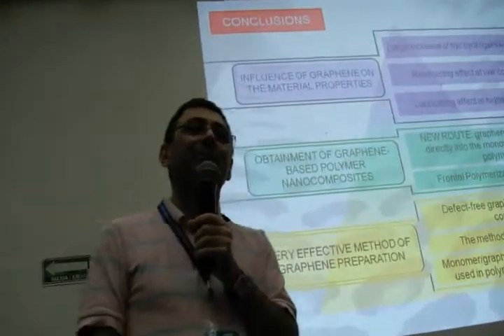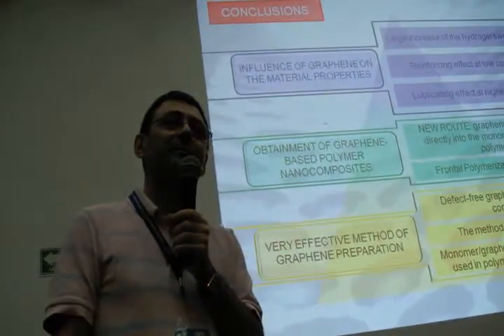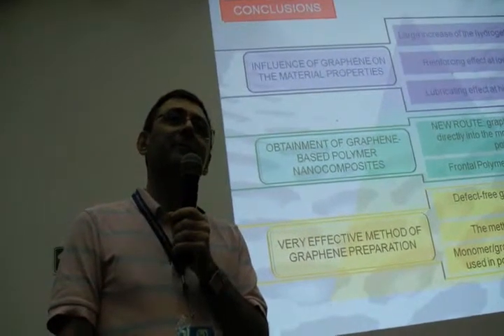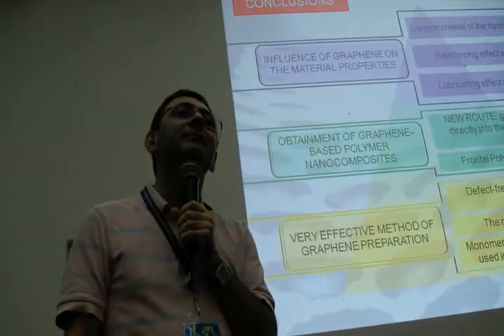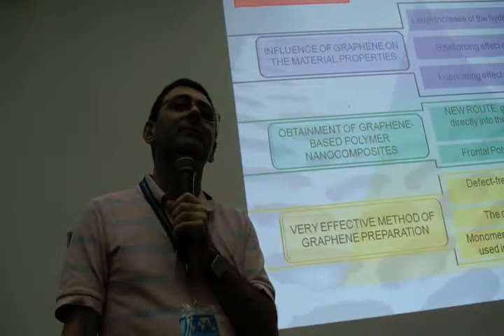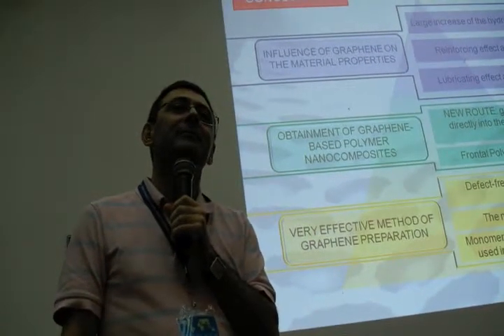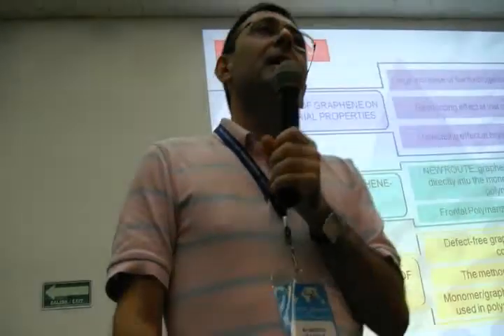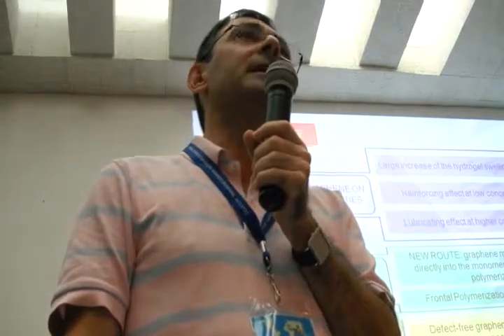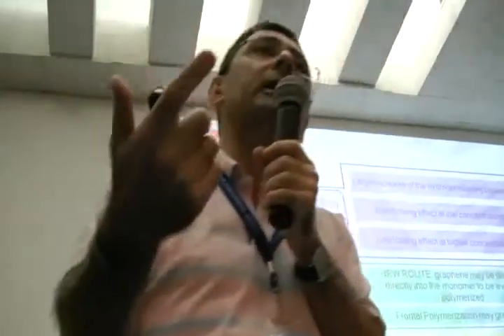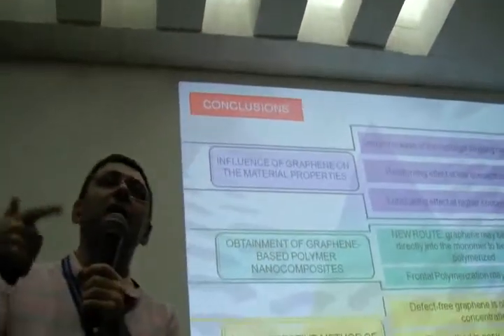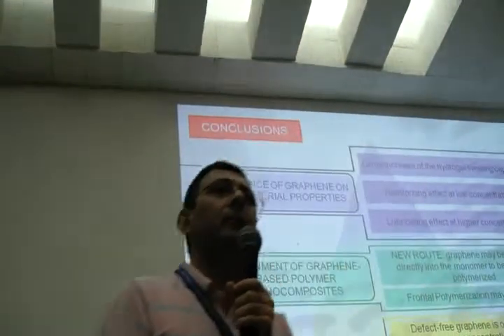Monounsaturated systems, right? Yeah. Because the problem you might have when you use the bisacrylate or bismethacrylate is that you're really forming a network, and if you have any fluctuations in the cross-linking density, that would be enough to give you Tg changes or swelling behavior changes and so on, and modulus changes. Yes, but we observe the same behavior in mono systems, for example N-vinylcaprolactam, without any cross-linking, in other systems which are not cross-linked. The behavior is practically the same. I think it will just be a nice double check. Okay. Just to be sure. Thank you.